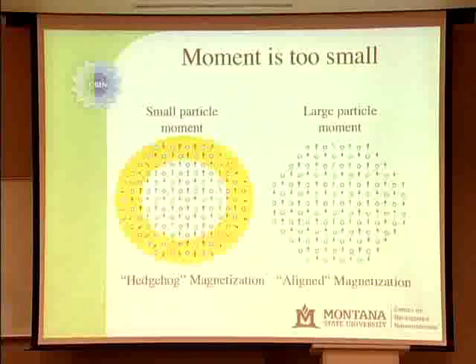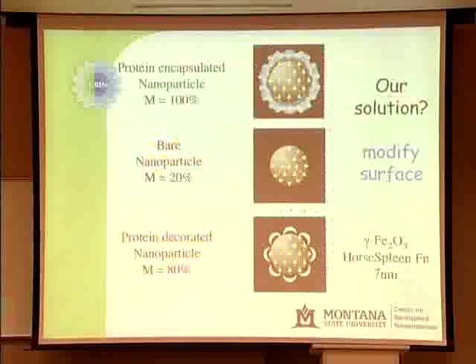And what we find is that when we have a particle by itself, it has this outer shell which is pointing always radially outward, whereas for the particle which is coated, we have the moment actually giving its maximum value. And we proved this by taking our particles, stripping the cage off, and that was as easy as putting it in bleach, which eats protein. Protein goes away. The moment went down to 20% of what it used to be.